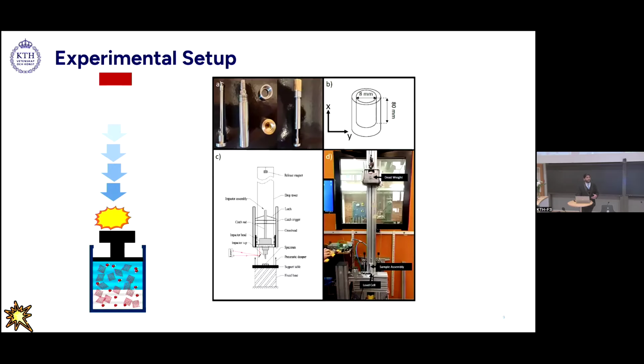And the ideology behind this design was very simple. We have a weight at a certain height, which drops on top of an experimental chamber, which is in the form of a piston cylinder arrangement. And inside this chamber, you have a cellulose and water mixture. Due to the impact of the weight dropping on top of this chamber, we will have a strong shock wave which will be sent inside the experimental chamber. And after many iterations, we were able to achieve this.